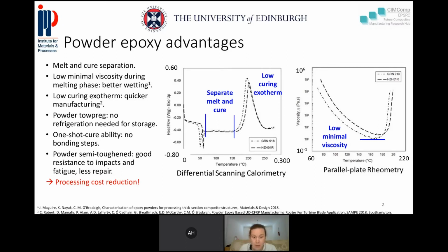So the second asset is the low minimal viscosity. As you can see here on the parallel plate rheometry, as the temperature is increasing, you can see the viscosity decrease before gelling. So basically, the viscosity you get is extremely low in comparison to thermoplastic. So that's basically the best of both worlds, because it's not curing at ambient temperature. It completely stays stable, and it has a low minimal viscosity. And when you think about it, if you can separate the melt and the cure, what you can also do is one-shot cure and co-cure different parts. And that's becoming extremely interesting, especially when we are thinking about preforms, right?